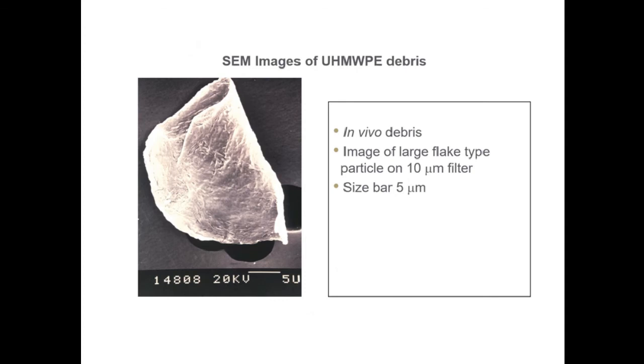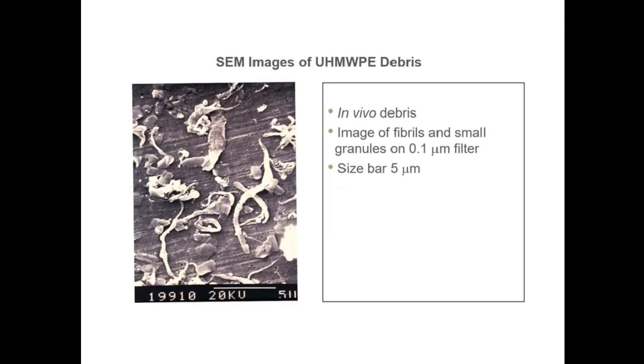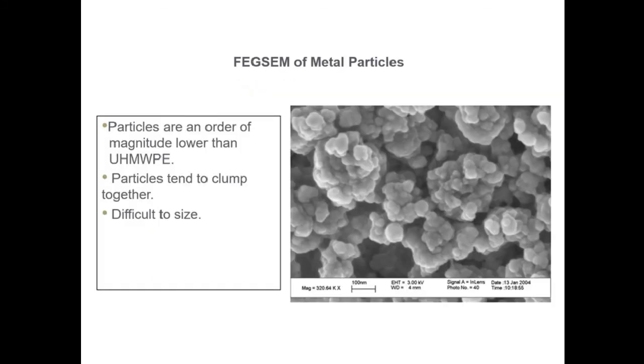This is an example of ultra-high molecular weight polyethylene debris seen under the SEM. And these are more polyethylene debris with different sizes and shapes, what we call fibrils and small granules of polyethylene material released by the implant. This is an image of metal particles. Usually they are an order of magnitude smaller than ultra-high molecular weight polyethylene. The particles are usually clumped together because of the protein surrounding them from the lubricant, and they are usually difficult to size because they are clumped together.